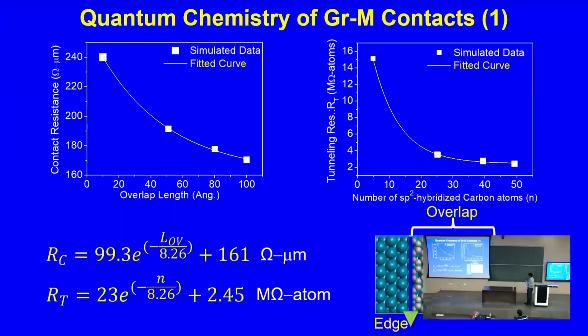So in one of the experiments, we were trying to play with the overlap length, and our idea was to find if there is an optimum overlap length which gives the best contact. The thought process was that the conduction will happen from this overlap region, right? So if I increase the overlap length, let's see how much overlap is needed. But what we found, which was very interesting, is when you plot the overlap length versus the contact resistance, right? These were all calculations, DFT and NEGF calculations in the beginning.